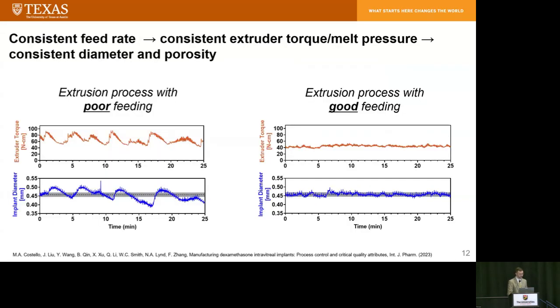So to summarize the key takeaways from the extrusion process, it's critical to have a consistent feed rate. This leads to a consistent extruder degree of fill, a consistent extruder torque and melt pressure. This leads to a consistent flow rate of melt through the die, and that leads to a consistent and on-target implant diameter and porosity. Yeah, the porosity comes in because the pressure in the extruder has an effect on the porosity.